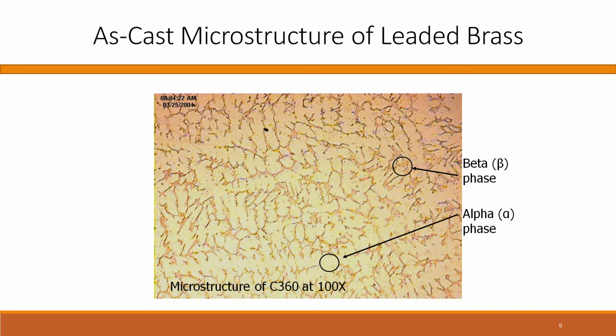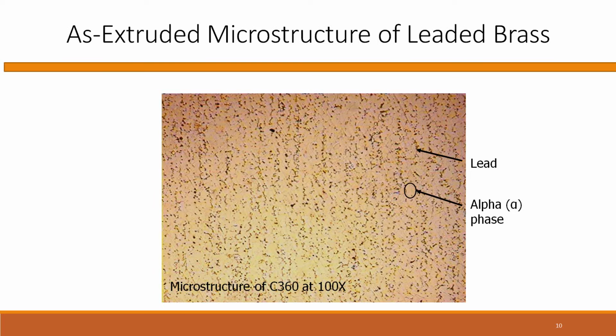When you heat the brass up for extrusion, it ends up changing the microstructure, so it's all that beta phase. And that's actually a good thing for extrusion because it allows you to extrude a very broad range of sizes from a given input billet size. But you don't want that there after it cools down. By proper manufacturing controls, as the extruded material cools off, the beta phase goes away. And that's good because beta is very prone to corrosion.